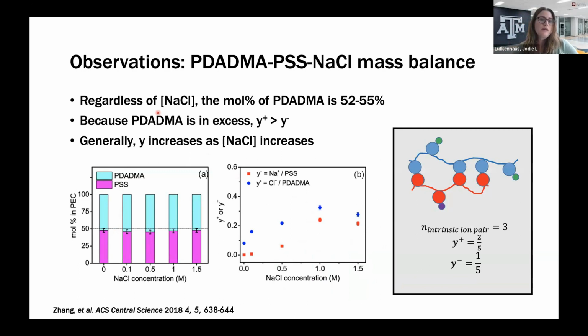Here what we observe is, regardless of the salt concentration at which I prepared the complex, I always have an excess of PDADMA, the polycation. We've seen this for years, and there are reasons for this. PDADMA is a little more hydrophilic. It has a different linear charge density. All of these can come together to make a slightly asymmetric complex.